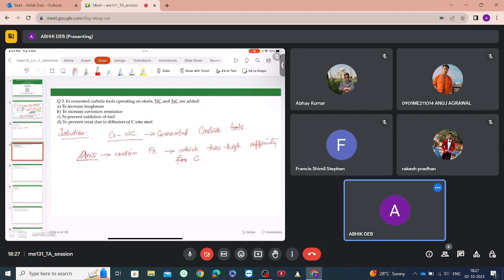So this results in the loss of carbon from the tungsten carbide. This is tungsten carbide, right? WC. So from the tungsten carbide there is a loss of carbon. Gradually the strength of the cemented carbide tools will decrease, or the hardness of the cemented carbide tools will decrease. Carbon diffuses to steel.